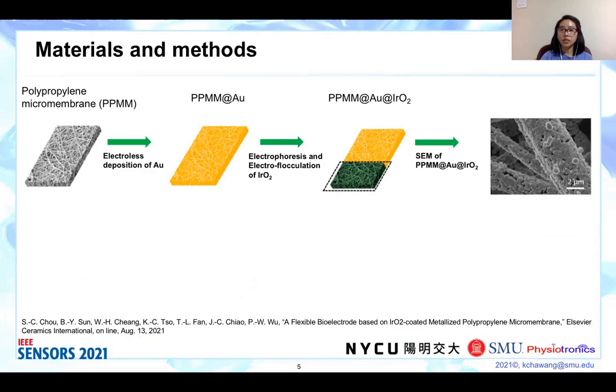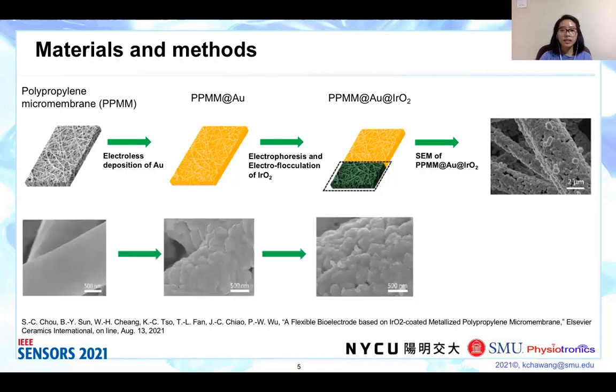The SEM image of the electrode surface is also shown. These SEM images show how gold and iridium oxide is deposited on each PPMM fiber. The first SEM image shows smooth PPMM fiber. Second image shows gold on PPMM fiber. And the third image shows how iridium oxide is deposited on top of gold.